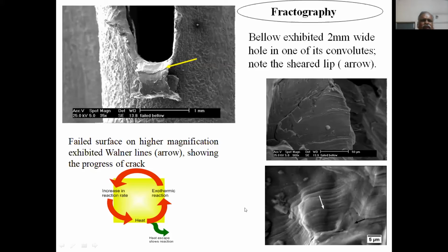That means there is some kind of interaction which is exothermic in nature. All of you know from 12th standard that when sodium interacts with steam, it is exothermic. In fact, sodium is liquid at 90 degrees Celsius, and when steam interacts, sodium plus steam will generate a huge amount of heat, and it can reach 800 degrees in no time. 800 degrees in no time. This will open out a very fine thin bellows material, and if a defect is present, it will open out through that, and that interaction causes Wallner lines, which are basically these lines that are microscopic.